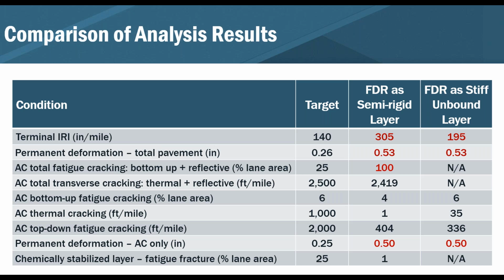But you can see where I showed before that the terminal IRI is different between the two, and certainly it is impacted by the reflective cracking, because you can see that some of that information is coming through. The target was 25 for the FDR as a semi-rigid layer, but actually it predicted 100, and so that said that all of the cracking is coming through, being mostly driven by the reflective cracking.